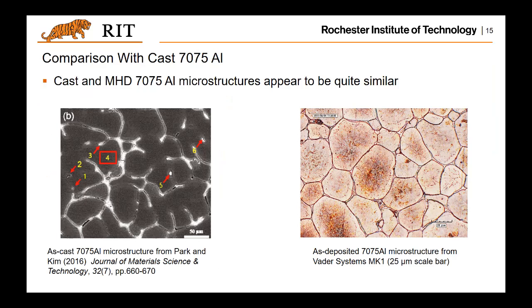Another comparison to be presented here is between the results printed using this metal printing process versus casting. Here it shows you the microstructure of the two results. As you can see here, it's quite similar. You cannot really tell the big difference between the two. So which again proves the effectiveness of this metal printing process, and the possible material property of the printing process is similar to what you have through the casting process. That is good.